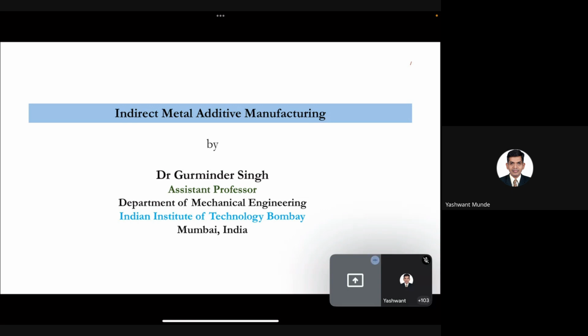Today I will present an unconventional, low-cost method which can be used in 3D printing to fabricate very difficult materials. For example, copper is very difficult to print by lasers because of its high thermal conductivity. When the laser falls on copper, the material reflects it and is not able to sinter properly to get 100% density. I will present an alternative method which can go up to 100% density.